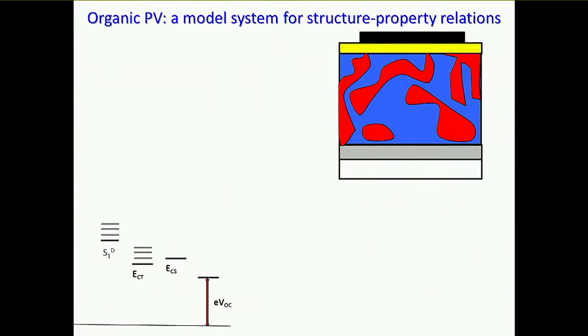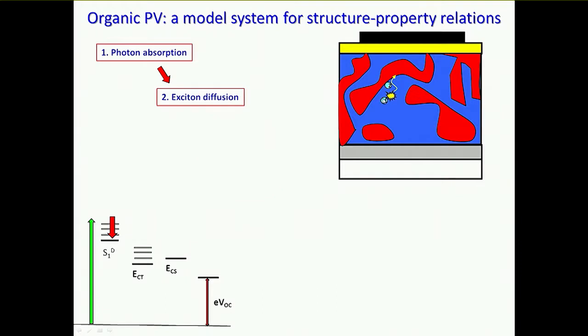So when we put that together into what is now the best studied model for photovoltaic energy conversion in organic semiconductors, which is called a bulk heterojunction or a dispersed heterojunction, we have our two semiconductors mixed together in some way that may be controlled, we'll come to that later, between two electronically different electrodes. And the sequence of stages that then proceeds is we will somewhere absorb a photon, and that will dump a certain amount of electrochemical potential energy into the system by exciting one or other of these materials into an excited state. And that's then followed by a process of diffusion, where the exciton reaches an interface, and as it does so, it will lose some of its electrochemical potential energy through a relaxation.